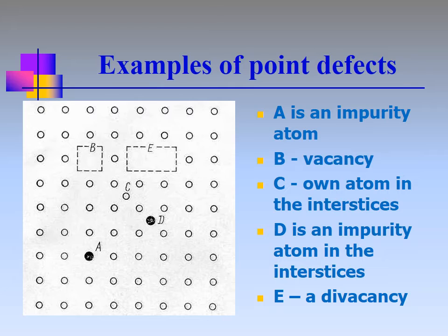The simplest of the centers of coloring is the F center. It consists of an anionic vacancy which acts as an effective positive charge. It keeps a free electron supplied, for example, by an excess atom of an alkali metal as a result of its ionization, or introduced into the lattice by an impurity atom. The F center causes the appearance of absorption bands in the visible region, as a result of which a colorless crystal becomes a colored one. There are other models of colored centers.